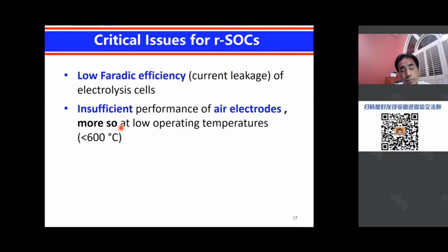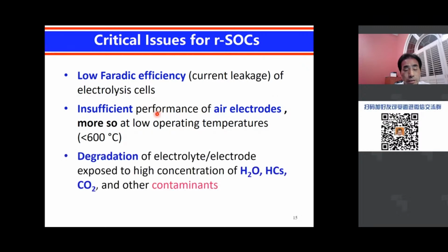One of the reasons we want to reduce the operating temperature is because at lower temperature, we can use much less expensive materials for cell components. But then the performance will decrease as the temperature is reduced. So one of the challenges is, how can we enhance the performance as the operating temperature is reduced? And finally, degradation of electrolyte-electrode interfaces, especially when it is exposed to water.